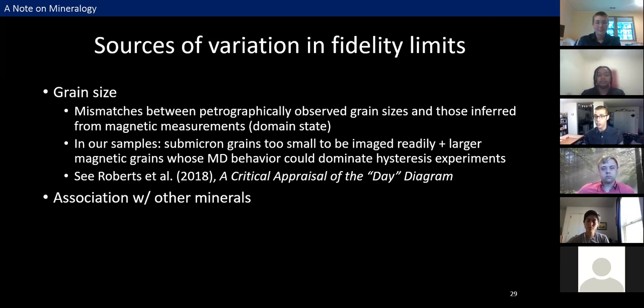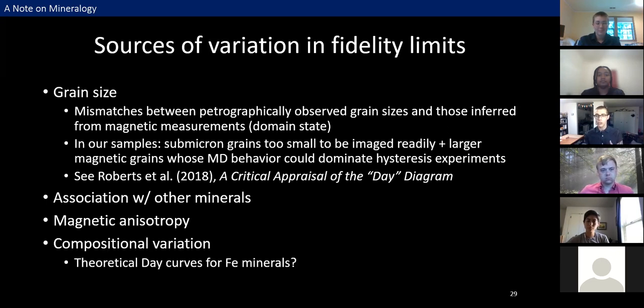We also took a quick look at the association of iron nickel grains with other minerals, and I didn't mention magnetic anisotropy, which could also be important. And I'm currently working on digging into compositional variations among iron nickel alloys, which I personally think is really intriguing. We've had some discussions about whether it would be informative to calculate theoretical domain state regions and Day curves for iron minerals, which wouldn't tell us anything about grain sizes without some experimental grounding, but could give us a sense of how far off we currently are from reality.